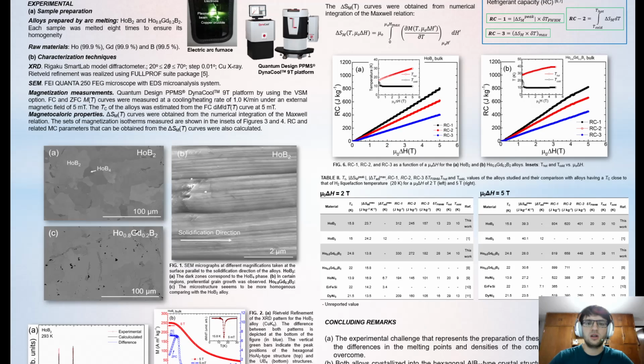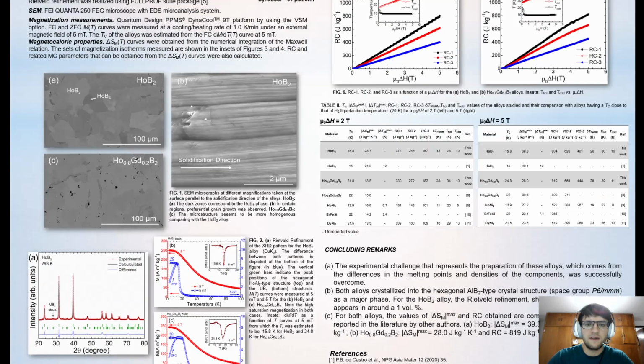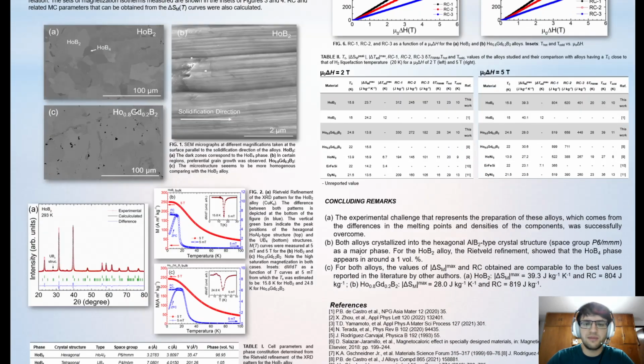In figures 1a and b, we see micrographs corresponding to the holmium diboride alloy. The first one shows the alloy microstructure, where the darker regions correspond to the holmium tetraboride phase. The second image shows a higher magnification micrograph, where we can see preferential grain growth along the solidification direction. In figure C, we see the microstructure of the gadolinium doped alloy, which is more homogeneous.